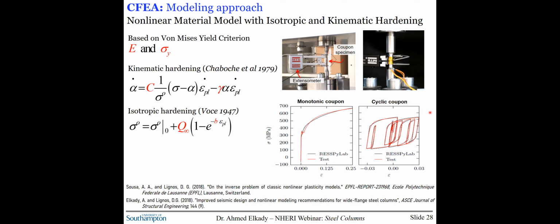Here you can see some comparisons with the coupon test and the calibrated material model. I would like to note that this material model, along with the recommended values for the parameters for the different steel grades, has already been implemented in OpenSees if you're using it. So please feel free to check this model and maybe use it in your fiber models and such.